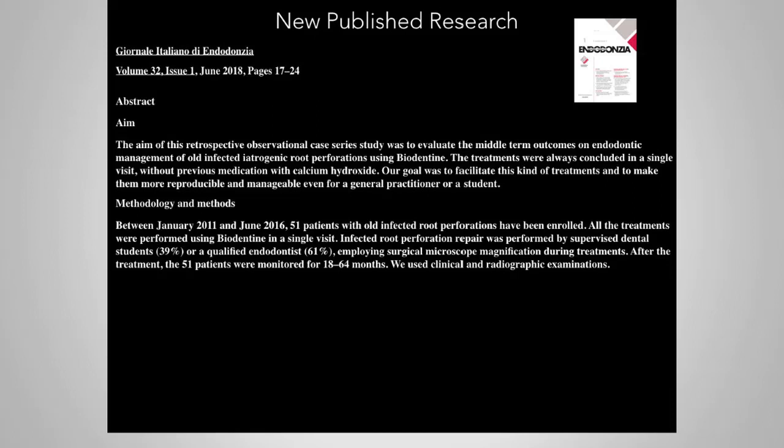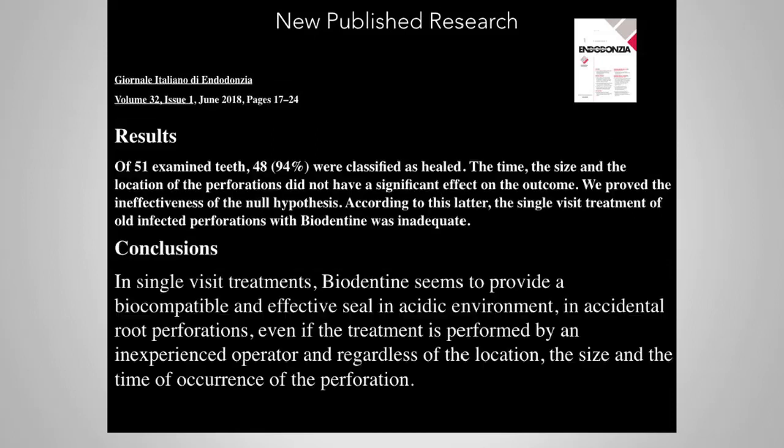So they used both of these, treated 51 patients, and monitored them over 18 to 64 months. They examined 51 of these teeth, and 48 were classified as healed. So 94% of these perforated lesions were healed.